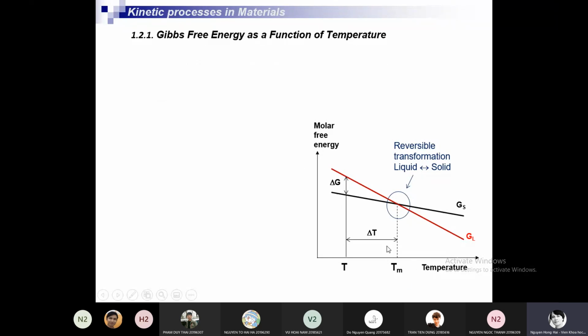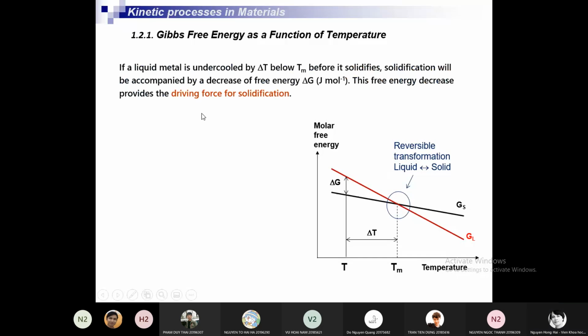So you see at this equilibrium temperature, the transformation is reversible. So how to make the transformation irreversible, from liquid to solid only, and not in the other direction? If the liquid is undercooled by delta T, until some temperature T equal to Tm minus delta T, we can say this liquid is undercooled by delta T below Tm before it solidifies. In this temperature range, the alloy is still in the liquid state.